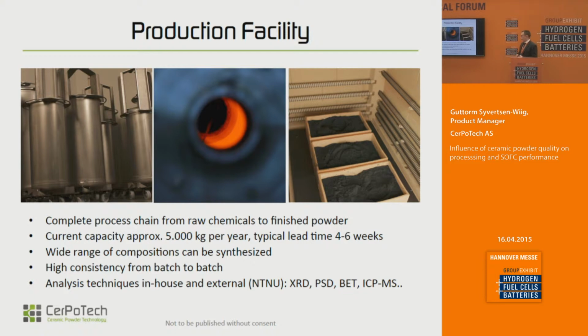Today we have a capacity of around 4 or 5 tons, depending on which material we're producing. We're still limited by nature, and that means the solubility of the elements in water. And for a typical medium batch size of 10 kilos or 20 kilos, we have a lead time of 4 to 6 weeks. Can be shorter. And it's a wide range of compositions, which I'll come back to.